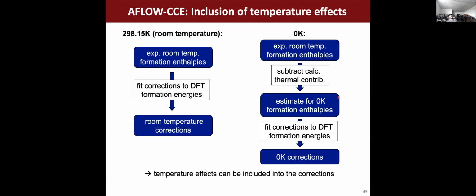I've already alluded to this, but the idea here is that we can get temperature effects. Okay, so we can get what the corrections are based on, because remember, the experiments are usually done at room temperature, and our calculations are done at zero temperature. And so we can take into account these effects. Okay, so we can get a room temperature correction and also a 0 Kelvin correction, where we subtract off the thermal contributions of the material. So basically the underlying point here is that temperature effects can be included in the corrections.